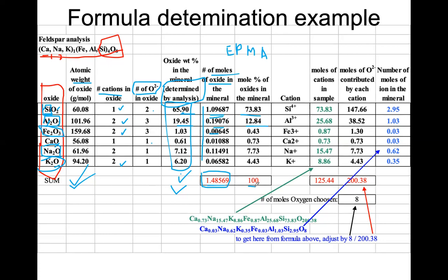The advantage of EPMA is this actually. It analyzes everything. It analyzes whatever is available within the mineral, right? So that means it should come to 100 totally. Ideally it should come to 100, but sometimes when you have some water molecule, for example, if you analyze hornblende, there are so many OH or halogen components there. So those are not measured by the EPMA. Anions cannot be measured by EPMA. But all the other cations will be measured, so you will end up with 99 point something.